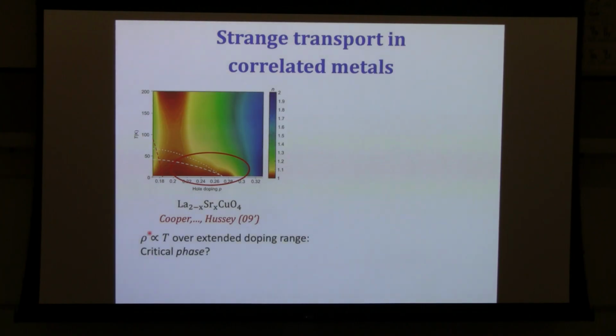So there seems to be a strange metallic phase or a quantum critical phase rather than a quantum critical point. And if we don't have a good theory for quantum critical points, this is much worse. And there is this apparent correlation between the end of the superconducting dome and the end of this strange metallic regime, where it starts to cross over towards T squared, which is what we would expect in a Fermi liquid.